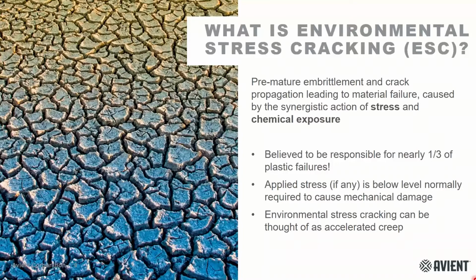So this is interesting. This is why I made the point that it's the synergistic action of stress and chemical exposure, because just stress alone can cause a material to creep. But when you bring in a chemical exposure, such as a disinfectant or some solvents within those disinfectants, they can really accelerate this creep phenomenon. And they have a parallel mechanism for material failure.